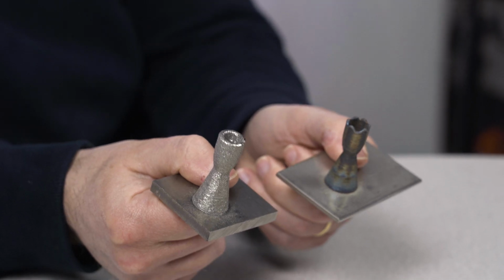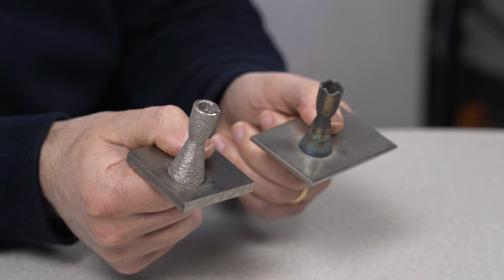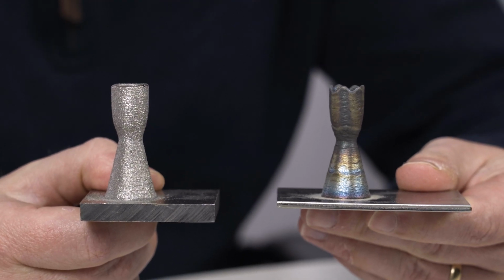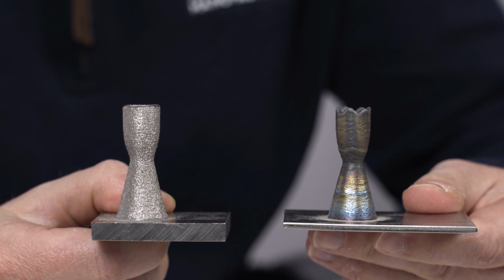There's another difference between the correct part and the error part that I want to point out, because since this is a heat transfer issue, these build plates, the base plates, are different thicknesses. Is that significant here? Was the base plate a heat sink? Actually, yes. In DED, the substrate, as we call it, is the small build plate on which you're building, and in some cases it might actually be part of the part. In this case, we're building the nozzle on top of that. As you can see, we used slightly thinner substrate material for that particular build, and that helps conduct heat away from the part as it is being built up. The amount of heat and the rate at which you can conduct heat away is different because of that build plate.